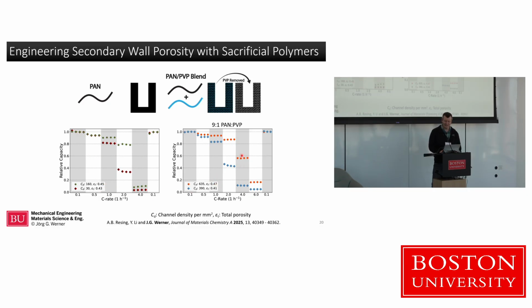But now if you look at this data point here, this is a 15-minute charge, and we can achieve almost 60% of the capacity, while here at a 15-minute charge, we essentially crapped out. So we shuffled more of our porosity around, but we did more than that. We somehow managed to change the connectivity of the porosity in the walls, which, if you remember my SEM images from earlier, we have no way of really quantifying. The resolution of that is in the tens, maybe a couple hundred nanometers, but it's a very mixed composite. So quantification of the connectivity of this pore space is very difficult, and we don't really know yet how to do it, but we see the impact that it has.